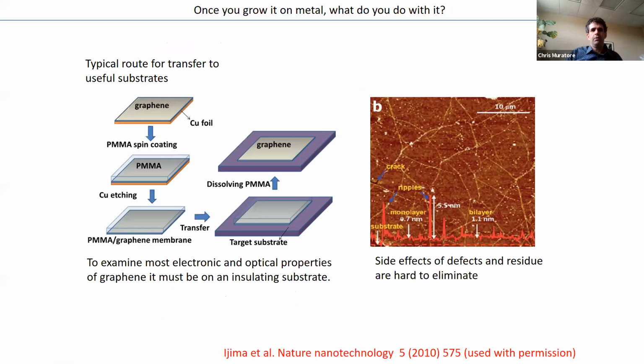So, all right, it's great to grow it on a metal, but you can't really do any characterization of this material on a metal, especially because graphene is pretty conductive. In fact, it can be one of the most electrically conductive materials that we know of. So if you want to do some characterization, you've got to take it off of that copper and put it onto something that's insulating. And so another transfer method is to apply a polymer to the surface, all over the surface. So PMMA is this polymer that's just spin coated on the surface, and then digest the metal on the backside. And now you've got graphene attached to the polymer.